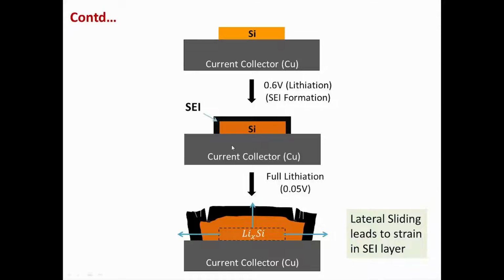What you can see is that as we are lithiating the silicon island, the first thing that happens is the reductive decomposition of the electrolyte, which results in the SEI layer formation. As we keep going down in voltage, there is lithiation of silicon and it will expand. As it expands in the lateral direction and in the vertical direction, it is applying some kind of strain to the SEI layer. And what we are looking for is how this strain affects the SEI. Would we be able to see cracking or delamination of the SEI layer? So my main approach is to use this kind of model system and use the AFM technique to see what happens to the SEI layer or look for its properties.